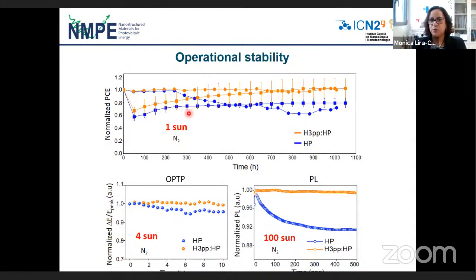But in general, what we observe is that at one sun, we observe very, very good stability. You can see that we didn't have any loss at the end of 1,000 hours. I think the worst solar cell had 2% efficiency loss. That's very impressive for a solar cell. So we observed this, and it was reproducible. You can see the error bars, and we say, well, there's something really happening with this additive.